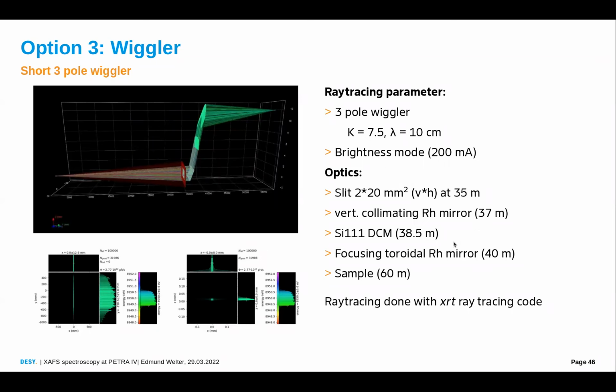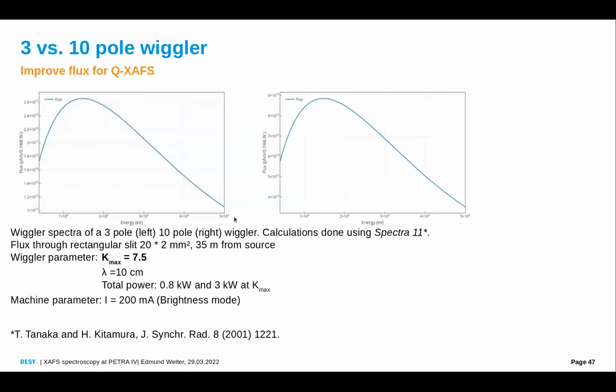So this is really the absolute upper limit, and one can expect that a factor of 5 to 10 gets lost somewhere on the way. And it also requires a first mirror at this position, which might or might not be possible. At least it would be very expensive to have that mirror. So it's a problem with collecting enough of the divergence. I also calculated it for a longer wiggler with 10 poles. Then we come to the region of about 10^14 photons into 0.1% bandwidth. That means about 10^13 photons within the silicon 111 acceptance.